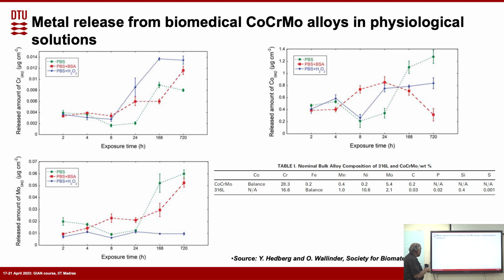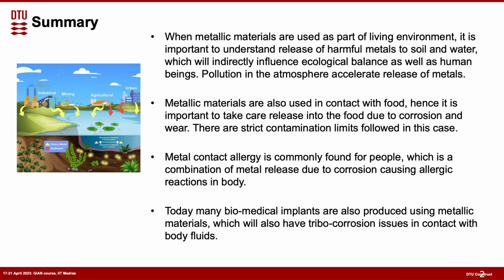And the important thing here is that compared to the stainless steel, the amount of chromium is also high in this alloy. So that also increases the chance for more chromium to come out. And this is a similar study, again showing how much chromium and different elements have been released. I think it's more like a summary of this one, with this graph showing different amounts like cobalt and chromium, how much is released. I think that's more or less what I have in this area.